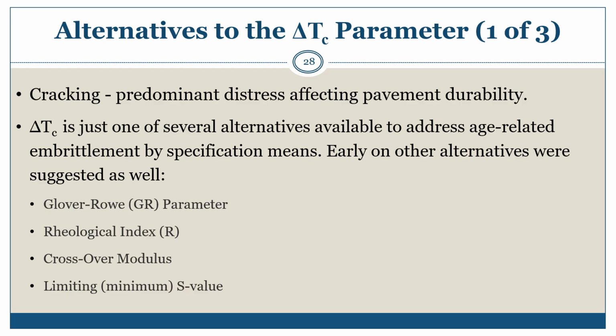Asphalt technologists have also suggested specifications limiting S at the critical M value. For example, specification limits for acceptable delta TC values, or specification of a minimum S value where the M value meets a current specification limit of 0.300. Establishing a minimum S value acceptance criteria is a reasonable alternative and does a reasonable job of screening asphalt binders with large negative delta TC, as well as limiting the effects of improper use of deleterious additives.